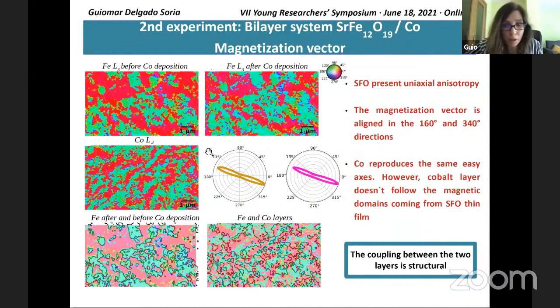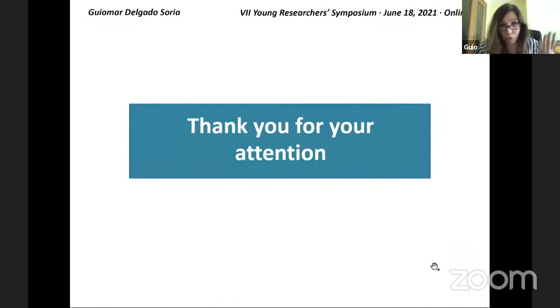But if you overlap both images, we can see that the regions, the lines, correspond to different magnetic domains and don't correlate. So we think that we don't have a magnetic coupling between both layers, but yes, a structural coupling. And thank you for your attention.